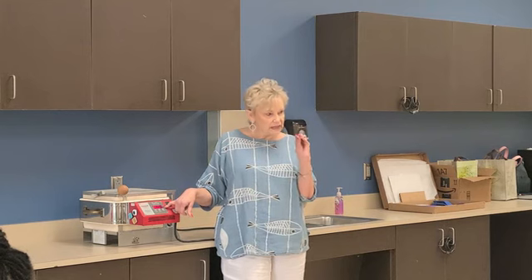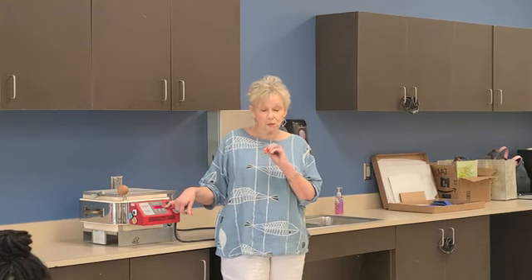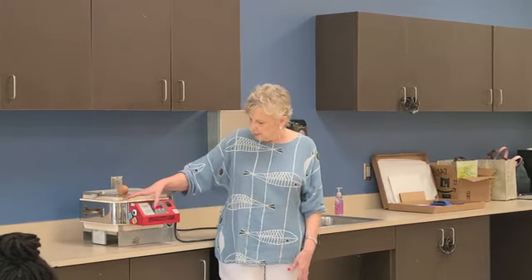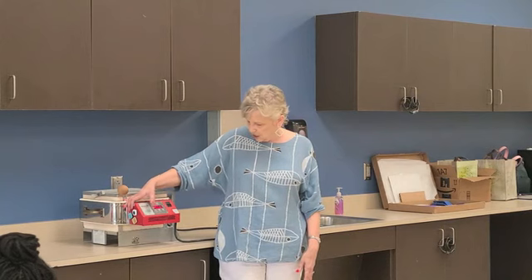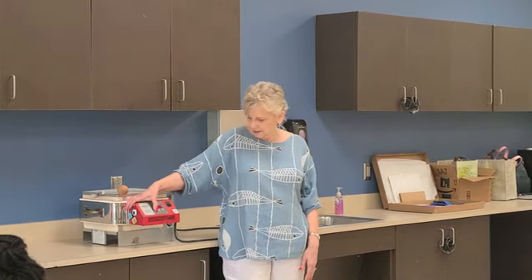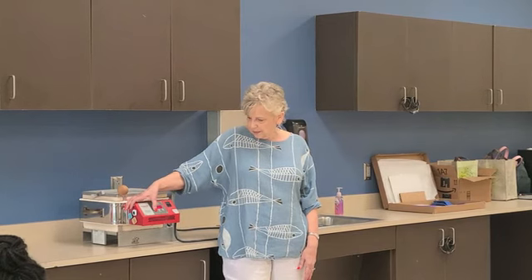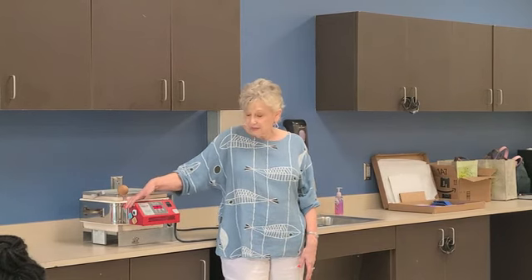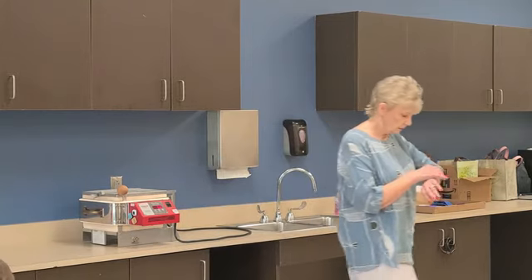If you have little tiny pieces and you want to cook it really fast, which you can with little tiny pieces, you don't have to go through all the other steps I'll talk about in just a minute. But we'll start there, and I'm going to go up as fast as it'll go to 1500 degrees. I'm going to hold it for 20 minutes, and then it's going to turn off. And when it finishes, it'll go beep, beep, beep, and they'll be round, and we'll see them, hopefully, depending on how long it takes. After all that, sorry.